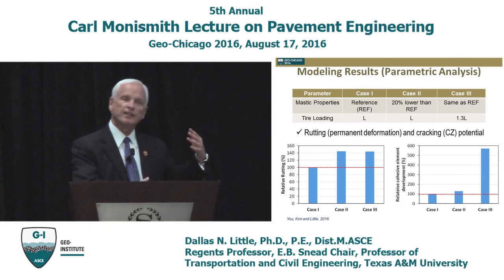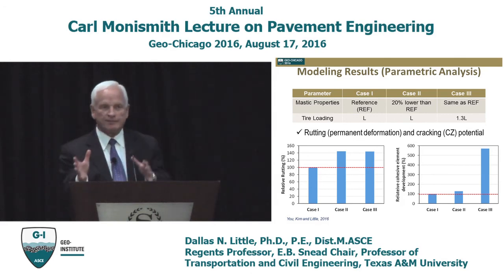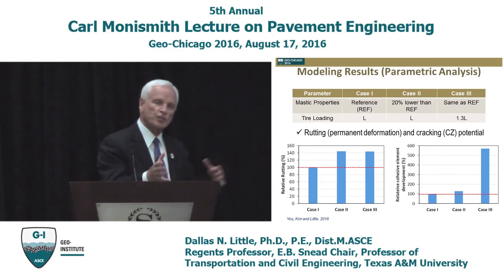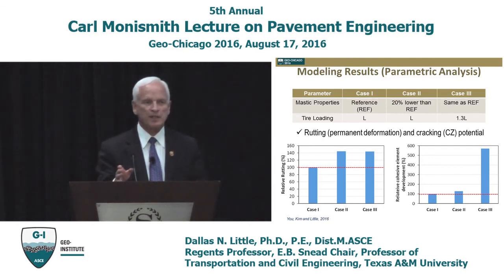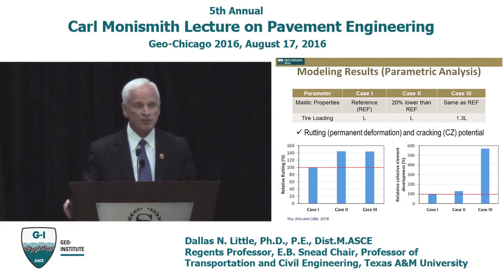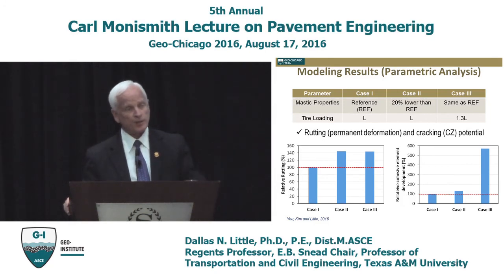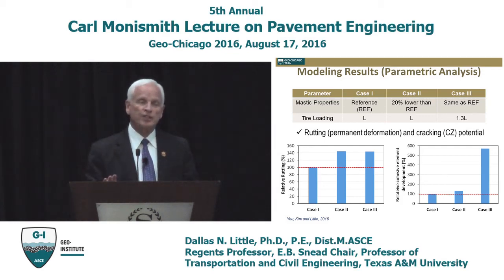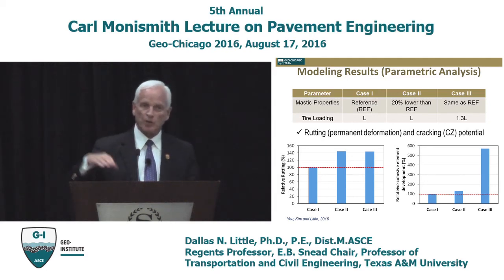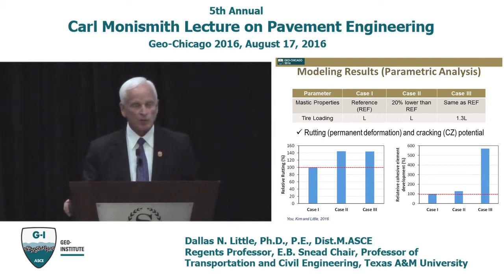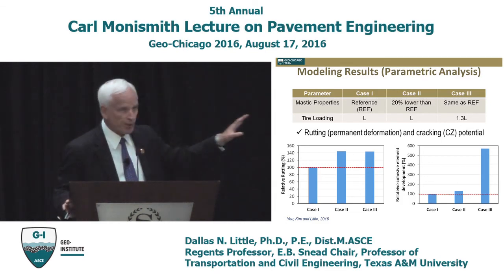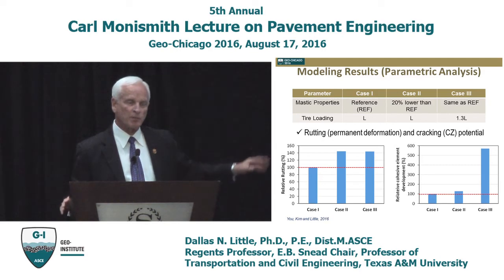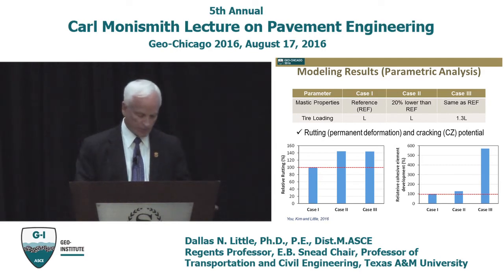Because there you're looking at general serviceability change. Right? You're looking at serviceability change, because that's what the 93 design guide is based on, delta PSI, change in serviceability, which is dominated by what? Subgrade rutting and roughness. Roughness first, subgrade rutting second. What is dominant, and cracking has very little to do with it in that 1.4 million load applications. Cracking was not a dominant factor. But where we're really interested in cracking, something like this can really help us understand it better. So it's a real advantage.